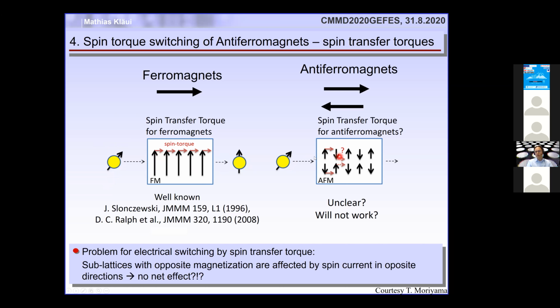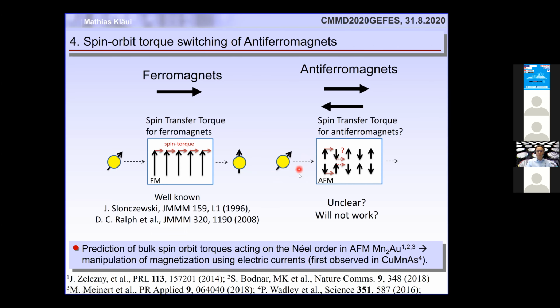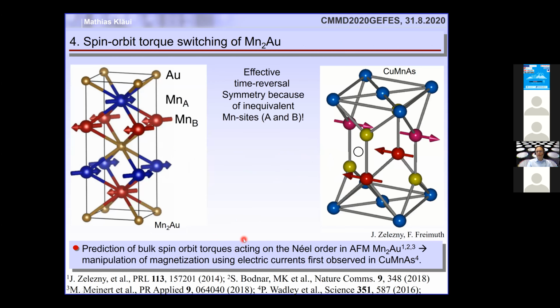So what you really want is a torque that acts on one sublattice differently from the other, and this is the so-called staggered torque. And this was first predicted in this paper here by Jakub Železný, Jairo Sinova, Thomas Jungwirth, and then first observed in copper manganese arsenide by Peter Wadley. And so fundamentally, this only works if you have a system where the two sublattices are inequivalent. And that is, for instance, the case in manganese two gold, where the blue sublattices and the red sublattices are inequivalent, so that the torque acting on the blue and the red sublattice is different. And the same holds for copper manganese arsenide.